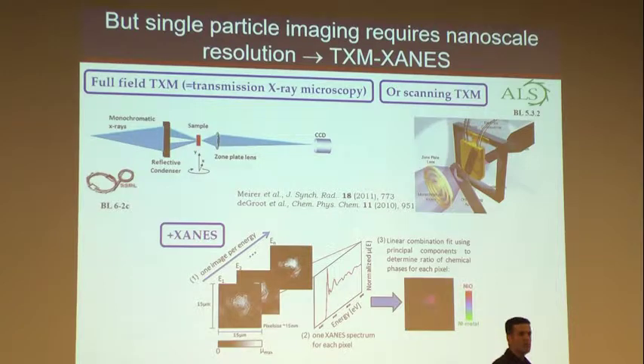And so it's very important for us to be able to combine that imaging measurement with some sort of chemical probe. And when we started this work, the easiest one was to combine with spectroscopy. If you have an X-ray beam that you scan through the absorption edge of an element, you know the oxidation state of that element, whatever you have a spectrum.